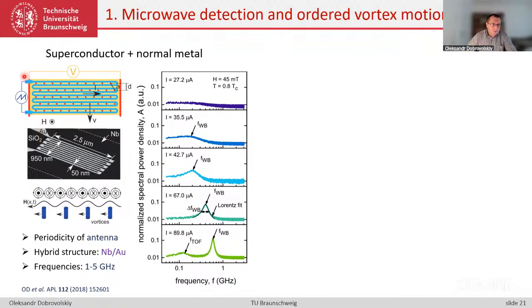So some preliminary experiment was conducted. In yellow here, you see a superconducting layer, which was overlaid by a normally conducting gold antenna formed as a meander-shaped nanowire. There was no direct electrical contact between the antenna and the superconductor. They were just stray-field coupled, so inductively coupled. And the magnetic field, which was perpendicularly oriented to the superconductor plane, populated the individual antenna periods with vortices, shown like that, which corresponds to a commensurate state.